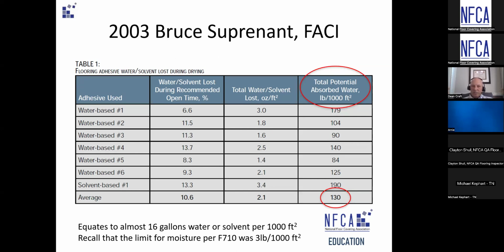Think about a resilient sheet that's basically impermeable. If the right open time wasn't allowed and just the surface of the adhesive skimmed off, but the body still had a lot of excess moisture and it's a non-absorptive surface, and then you lay in a resilient sheet, where's the excess water going to go? Yeah, it just turns into an emulsion like paint, and it's in contact with a high alkaline material. So the residual alkalis in the concrete start going into solution. And now the pH of that adhesive starts going up to a point where the adhesive itself starts breaking down, because of the more and more alkalis it's exposed to.